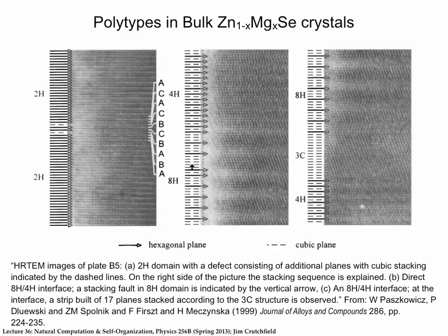I should note that this crystal is zinc selenide that has been doped with magnesium, and the doping, the X here, is somewhere between 0.17 and 0.21. So it's got just a little bit of extra magnesium in it. And when you do that, it tends to induce this behavior. You get this guy that turns out to be polytypic. And that's another way that you find polytypes is by doping, because that can change the interlayer energy between these layers, and it can cause layers to become nearly degenerate and stacking arrangements to become nearly degenerate as they're ordered. Questions?